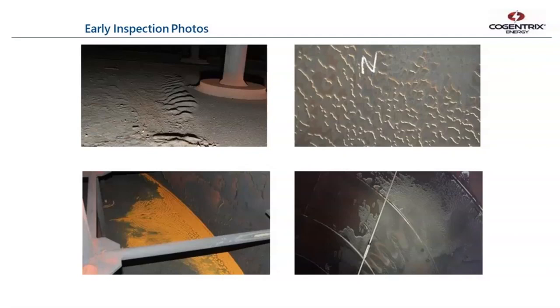Farther downstream is the bottom left. You can see orange rust. That's where there's a little puddle of water and the metal's unprotected under it. And then the lower right is the typical area of the turbine exhaust duct. That particular spot is near where a bypass comes in, and it just blasts all the passive oxide off of the walls, and that's what you're left with, is a giant spot of bare metal.